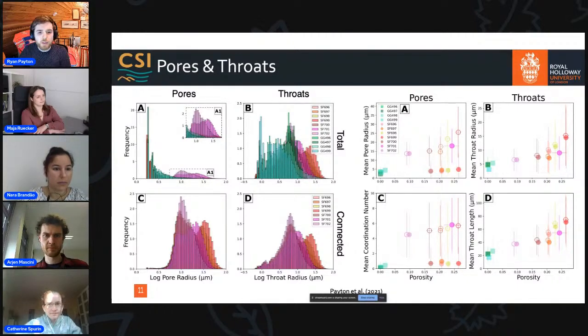And we were unable to see anything like extra mineralization, clays and that sort of stuff; that didn't appear to be present. It would be nice to carry out some higher resolution imaging if that becomes available to me, and then be able to try and factor that in if there is any microporosity present. There are potentially plans to do some FIB-SEM to look into that. But currently everything that I've shown is based on the assumption that this is the macro porosity. Of course, the microporosity is something that's incredibly important, particularly in those Glasgow samples, which are so heavily cemented. If there were a lot of microporosity present there, then that could be a real game changer for what the overall porosity is. So currently, based on macro porosity, this is what we see, but it would be really nice to consider the microporosity too.